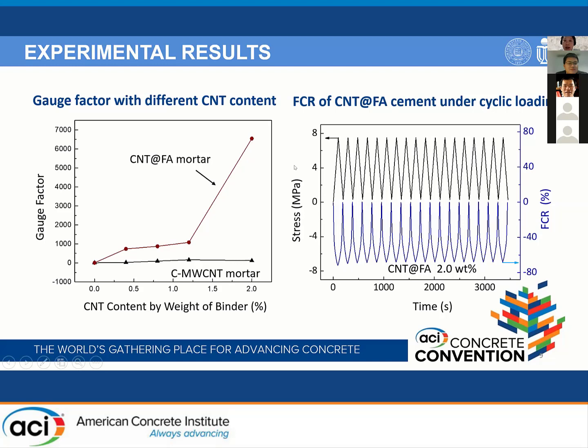And then, in order to investigate the piezoresistivity of CNT and FA cement mortar under cyclic loading, we detected the FCR of this type of cement composite under cyclic loading, and the result is shown in the right figure. From the right figure, we can see that for the CNT and FA cement mortar at 2% of CNT addition, the resistivity decreased with an increasing compressive load upon loading and increased to the initial values upon unloading, suggesting that CNT and FA cement mortar exhibits a reversible piezoresistivity under cyclic loading. And during the loading, the maximum value of the fractional change in electrical resistivity reached 70%,